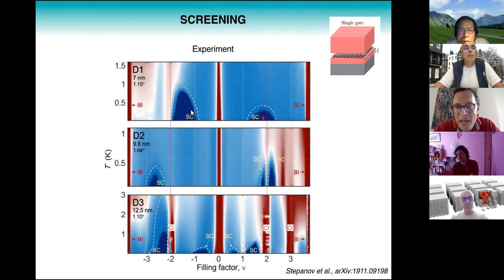And you see that the phase space of the correlated insulator states seems to be taken up by the superconducting domes. Now, this is, of course, very interesting, because what it tells us is that this material might, after all, be very different from the cuprates. So for the cuprates, the dominant view is that the superconducting state is very closely related to the correlated insulator state. In particular, what many people think is that spin fluctuations inherited from the antiferromagnetic parent state give rise to the Cooper pairing. So correlated insulator states and superconducting states are strongly linked. But here this doesn't seem to be the case. Here the correlated insulator state can completely disappear and the superconducting states can become stronger.